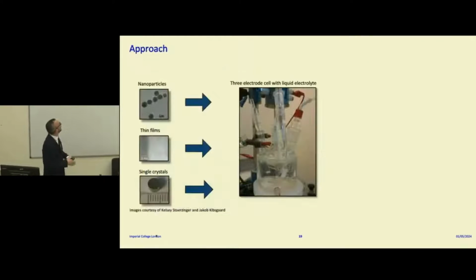For example, we often look at size-selected nanoparticles. These are typical nanoparticles, 5 nanometers across. Or we could look at oriented thin films, or even single crystals, which are 5 millimeters across. It's quite interesting to consider the length scale: there's about a million times difference between the size of these particles and this single crystal here. Whereas in an actual device you often use a polymeric solid electrolyte, often what we use instead is a liquid electrolyte, and we rotate the electrode to stir the solution and bring reactive gases to and from the electrodes we're studying. Using this, we can study the role of a catalyst under very well-defined conditions.